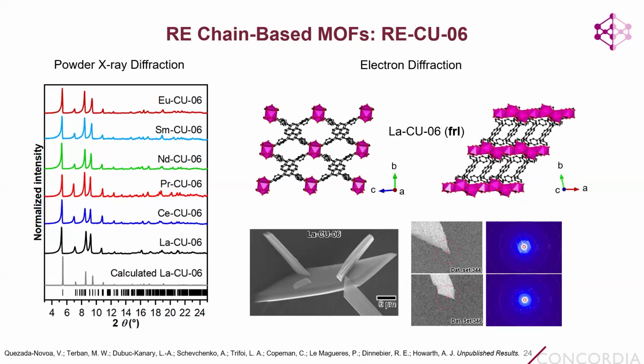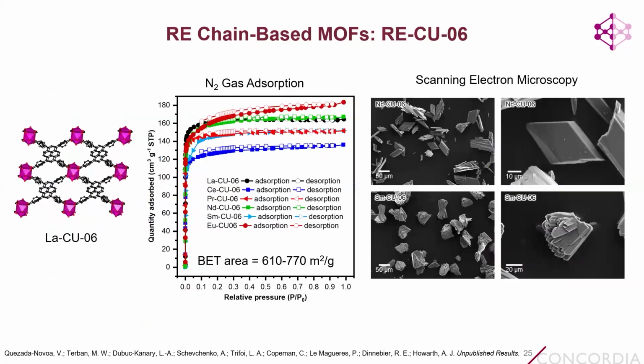And Pierre was able to solve this full structure by merging 5 different data sets. And we were able to plug this into ToposPro to determine that the topology is FRL. Again, this is a MOF that is permanently porous with surface areas ranging from 600 to 770 meters squared per gram. And then you can see those crystals under this scanning electron microscope. So they do not look like crystals that, to me, you would be able to get a structure from. So it's very exciting for us.